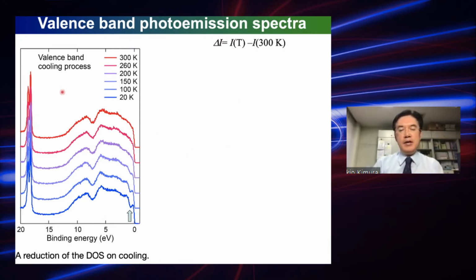So I'd like to show you the valence band spectrum in the cooling process precisely, and you see some broad feature near the Fermi energy at room temperature. By decreasing temperature, you see some changes, especially from 150 Kelvin. You see the growth of the dip at a binding energy of 0.75 eV. Accordingly, you see the appearance of the peak at the Fermi energy.